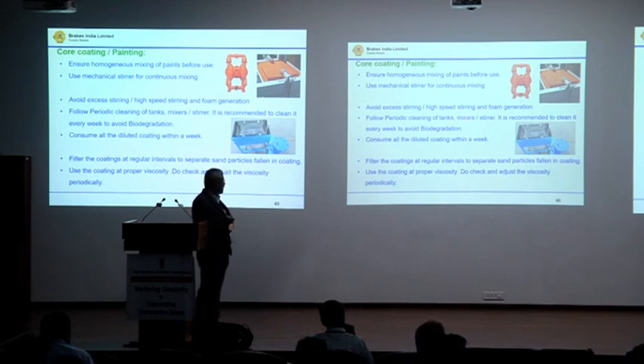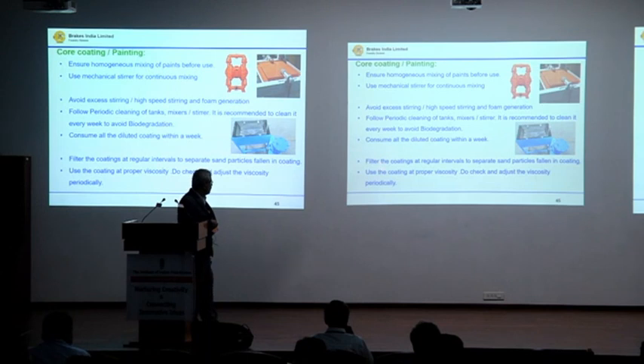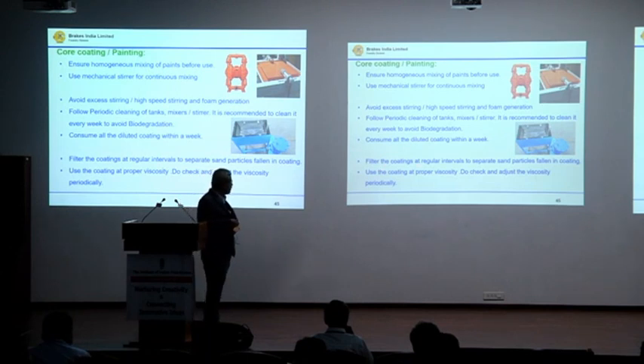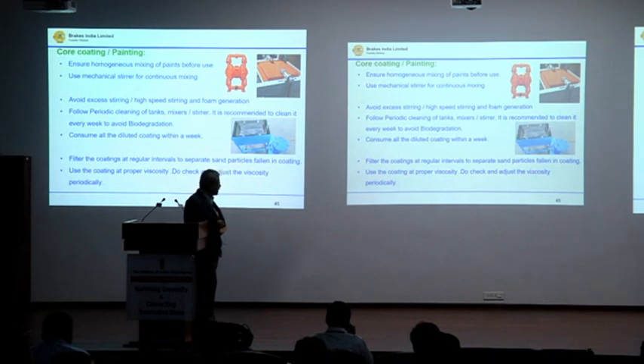Follow periodic cleaning of tanks, mixers, and stirrers. It is recommended to clean the tank every week to avoid biodegradation. Consume all diluted coating within a week. Filter the coatings at regular intervals to separate sand particles that have fallen in the coating. Use the coating at proper viscosity, and check and adjust viscosity periodically.